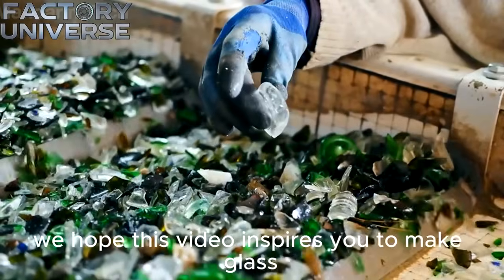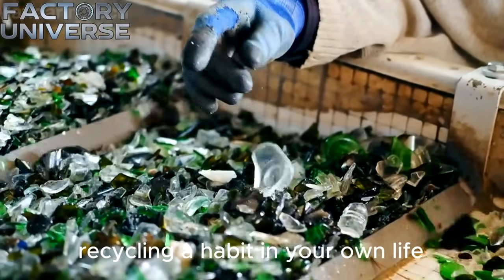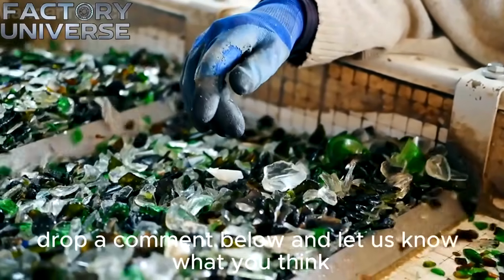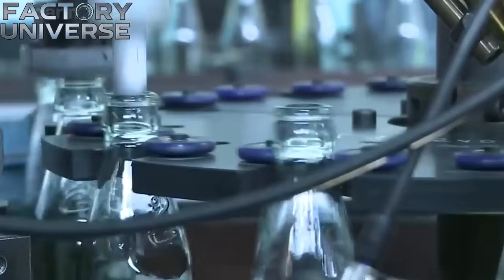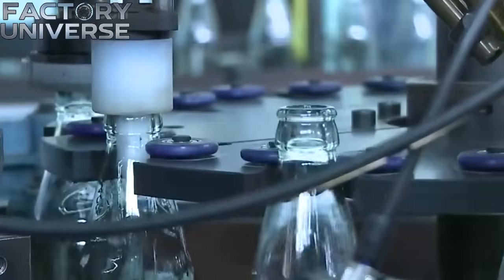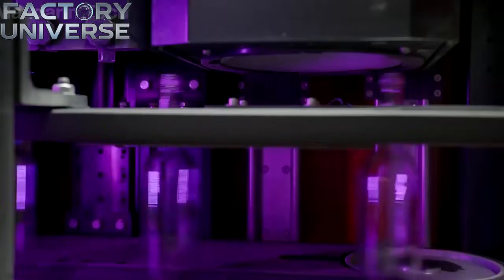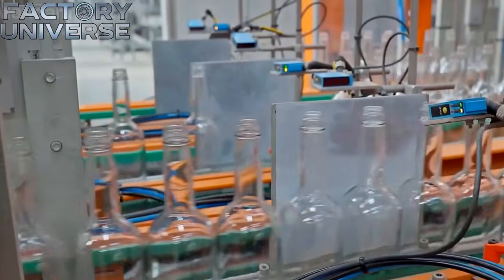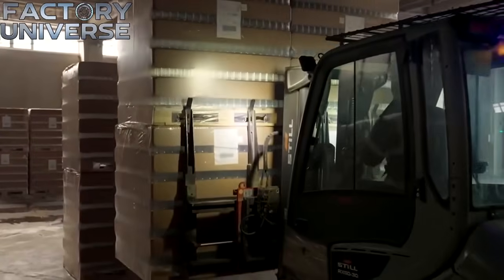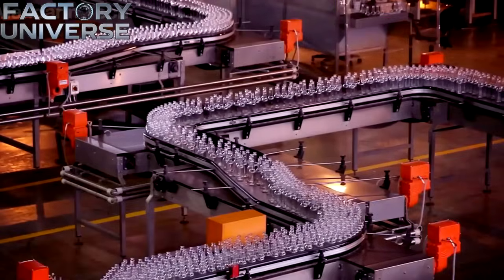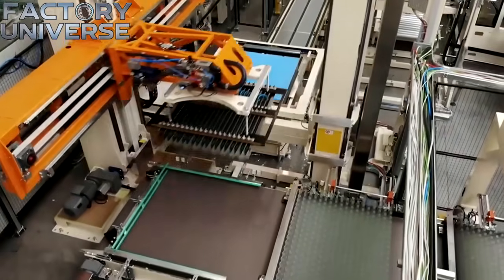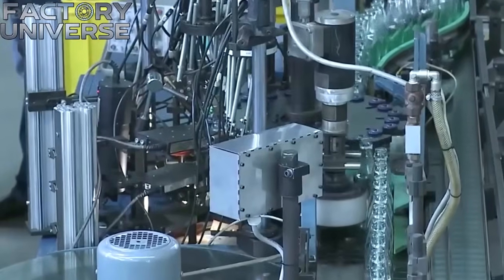Why must this cooling stage be conducted with such calculated slowness? At first glance, the process seems like a simple delay in the production chain, but in reality, if the glass cools too rapidly, internal stresses will cause the bottle to shatter instantly. This thermal treatment stage takes its time, often lasting several minutes and sometimes stretching to 40 or 50 minutes depending on the thickness of the glass wall. The process is only gaining momentum.